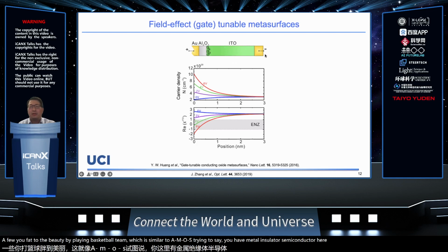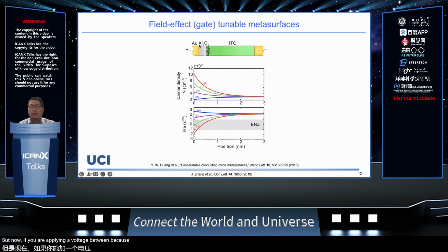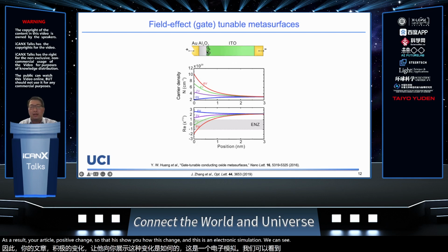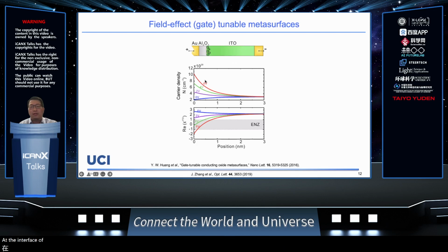Now if you apply a voltage in between, because you have an insulator here, your electrons will accumulate. They cannot pass through. As a result, your electron density will increase significantly, and your optical property will change. To show you how this changes, this is an electronic simulation. You can see at the interface of ITO, by changing the voltage, the carrier concentration can increase by maybe an order of magnitude.